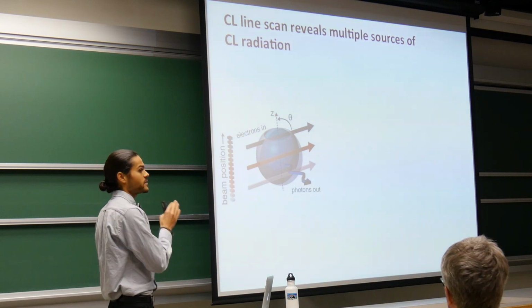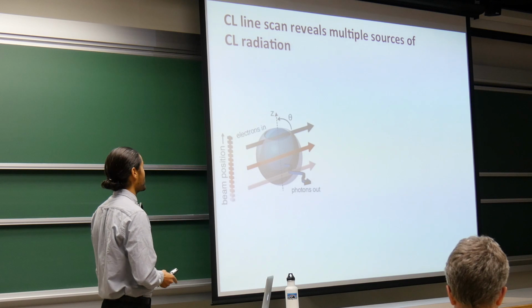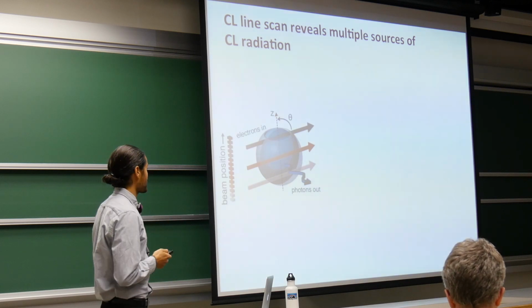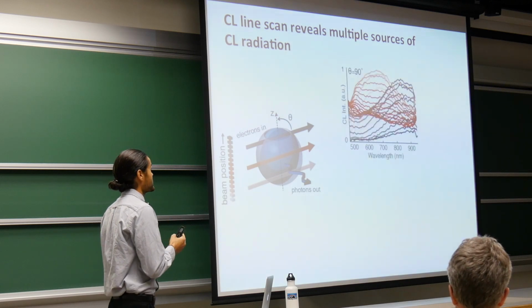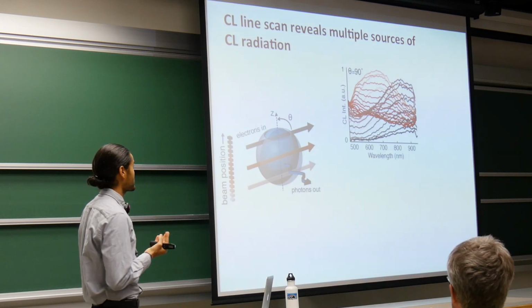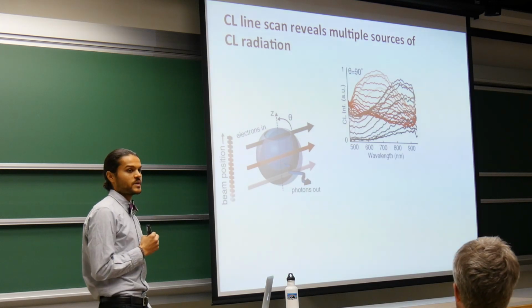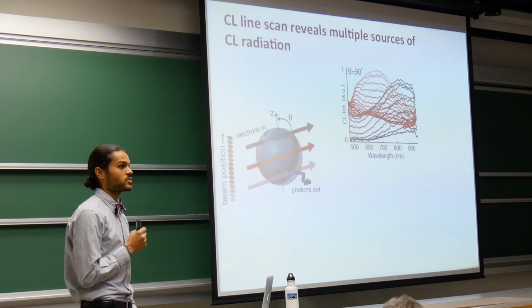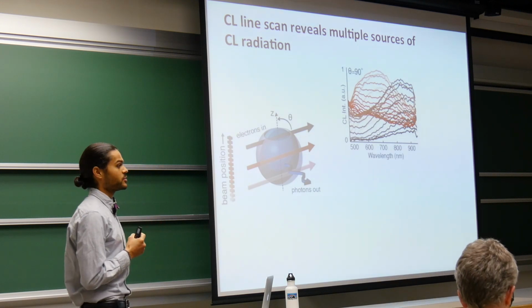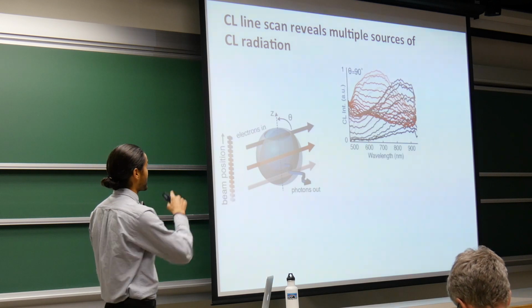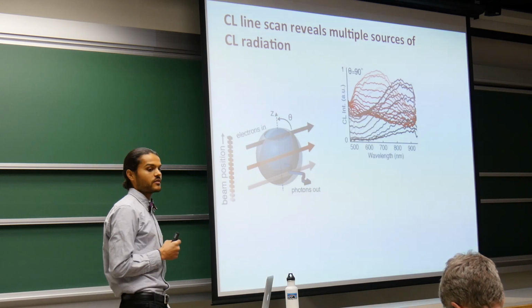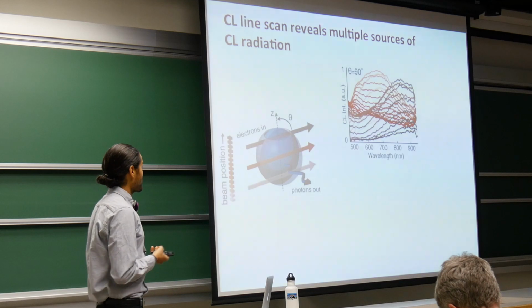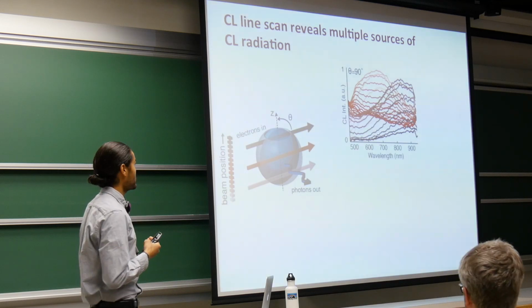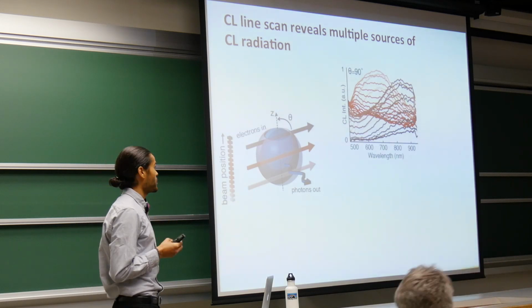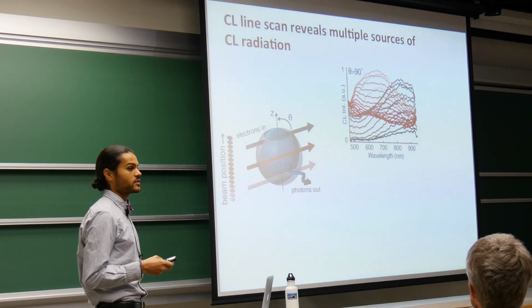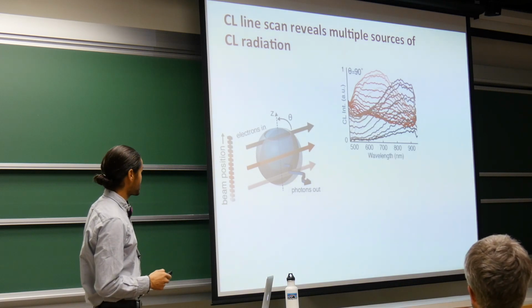Here we're going to sweep the beam in a one-dimensional line scan from the base of the crescent up through the center towards the tips. And when we do that, we can see two particular spectral features. The first one: when the beam is passing through the base of the crescent, through the thickest portion of gold, we see this material luminescence from these interband transitions coming out in these lighter colored lines, peaking around 600 nanometers. When we sweep the beam up towards the tips of the structure, where that plasmonic mode is supported most strongly, we can see that the luminescence peaks again around 800 nanometers.